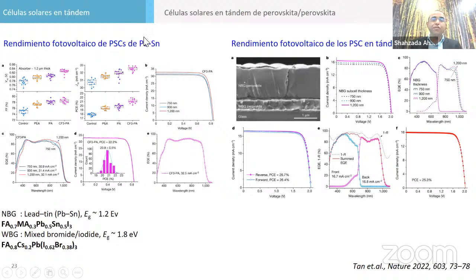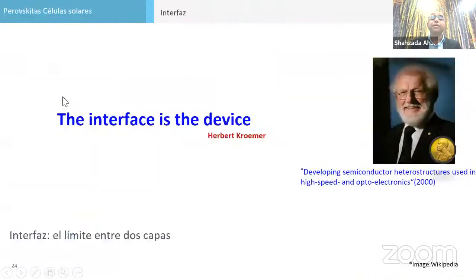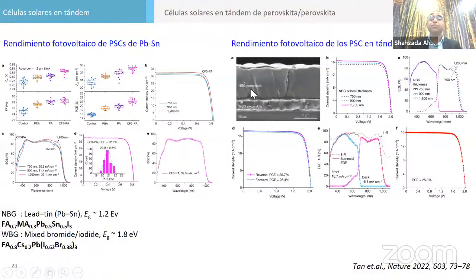If you make a mixture of lead and tin, this is also very good, and it gives a band gap very close to 1.2 electron volt. You can achieve a 1.2 electron volt band gap if you do 50-50 lead and tin with formamidinium and methyl ammonium. These people have achieved an efficiency of almost 22.23% by doing so. The band gap of 1.1 or 1.2 is very good for a tandem approach.